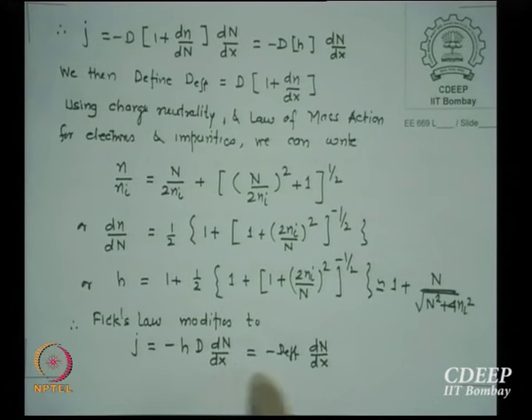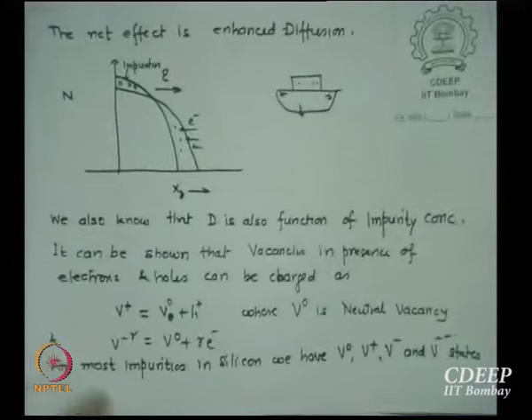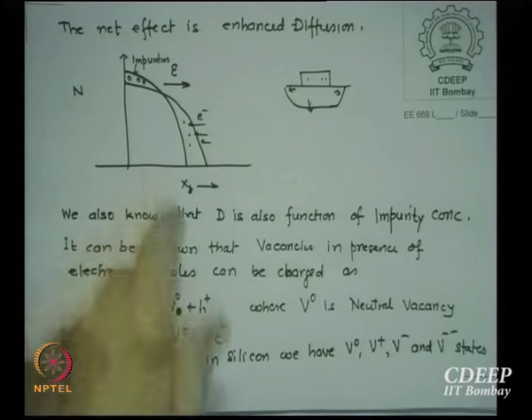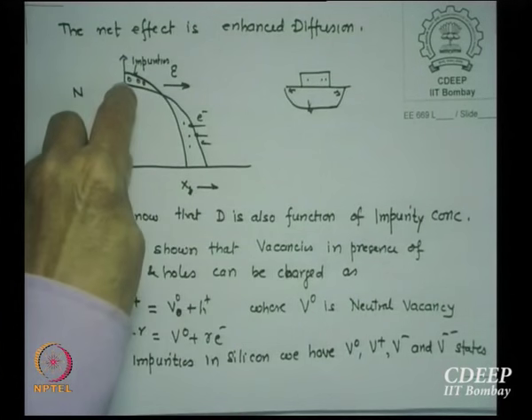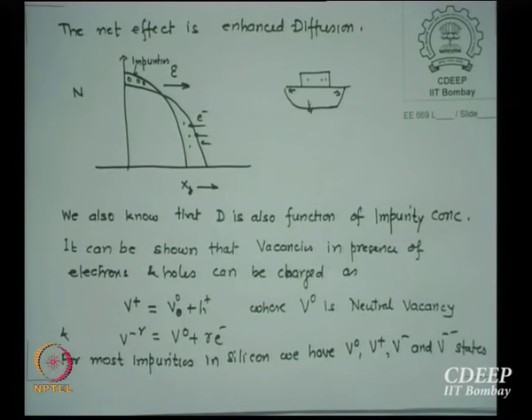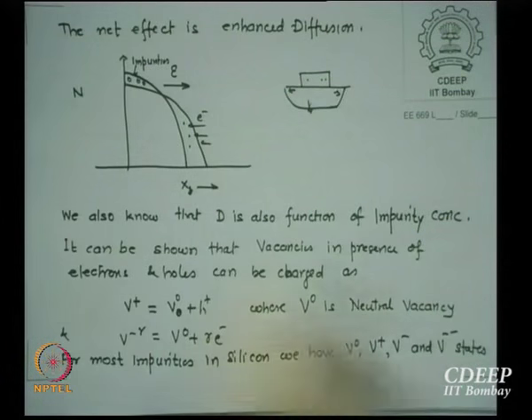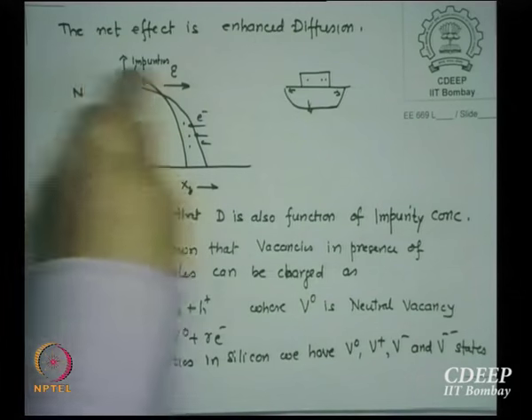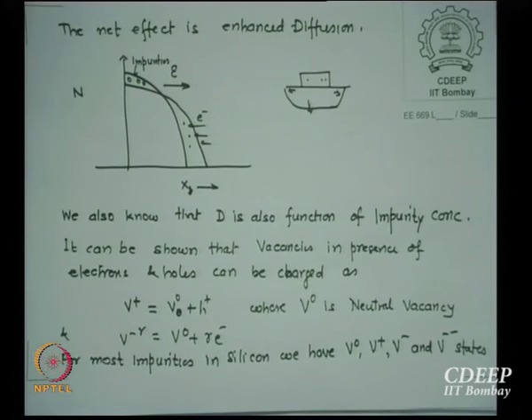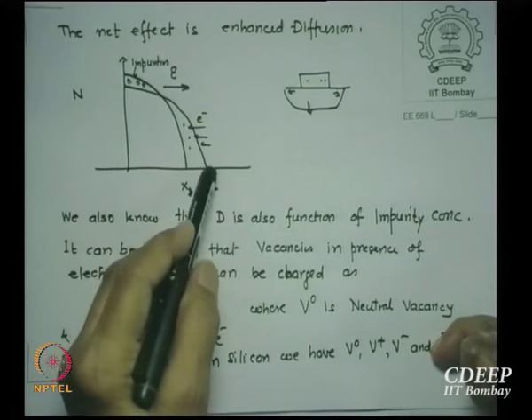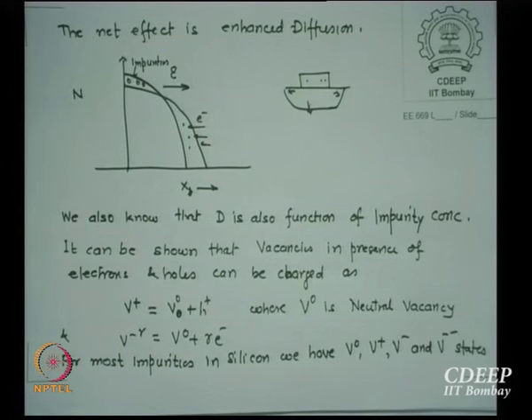So J is minus H D dN/dx, or D effective dN/dx. If you have noted down, here is the effect it can give. Let us say the initial profile was this one, and there are impurities here and electrons here which have higher mobilities. Remember, electrons have higher mobility than ions, so electrons move faster. That is why a depletion layer is created which increases the electric field. If there is an enhanced electric field, impurities try to follow it, and the new profile is different. This was the initial profile and now this is the additional diffusivity seen. So it actually goes in, but the net concentration remains the same. Surface concentration slightly reduces to adjust for the number of impurities being pushed.